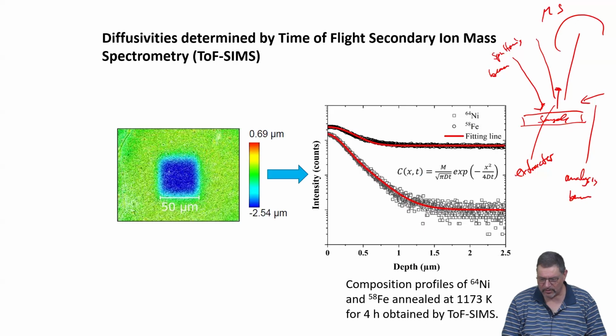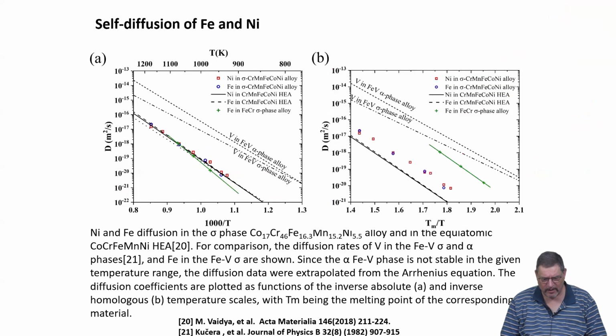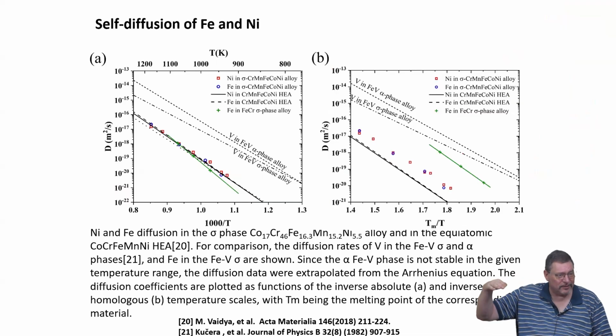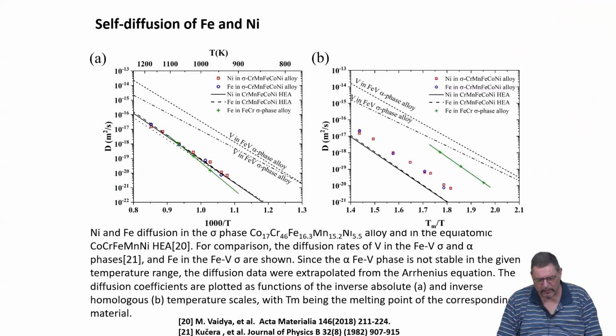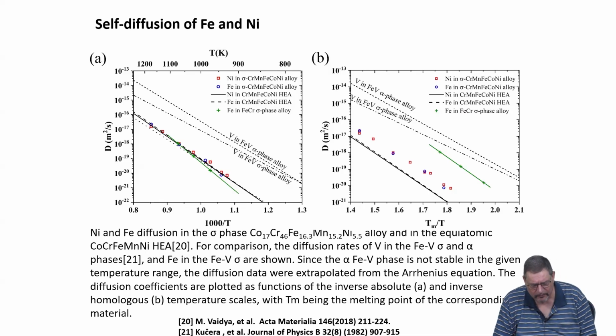Yeah, you just use the normal fitting procedures, and then you can, again, do this after you have annealed the material at different times or at different temperatures, giving you diffusion profiles. And here the nickel and the iron diffusion in the sigma phase is shown, again, for both ways to plot it. And for comparison, the diffusion rates of vanadium in the iron-vanadium sigma phase and the alpha phase, and iron in the iron-vanadium sigma phase are shown.